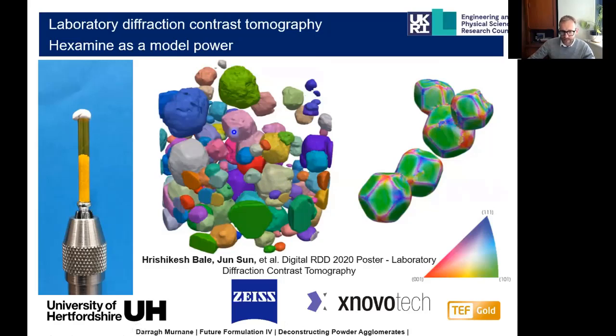So in this centralized image here in the center of the screen. So if we're able to identify the orientation of the particles, and we're able to identify the individual crystal faces or face families of those particles, and we're now able to superimpose on top of that the micronized particle phase that we pick out from our phase contrast, we'll be able to identify which particular crystal faces or family of crystal faces the majority of the drug adheres to.